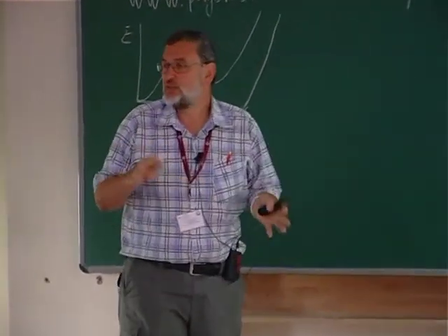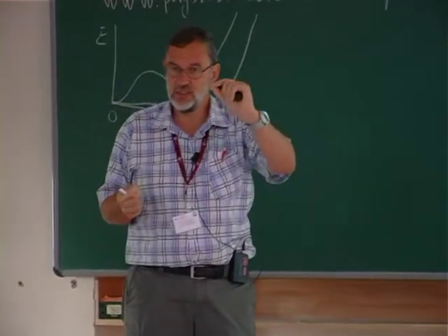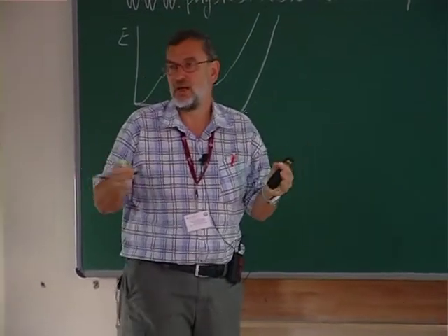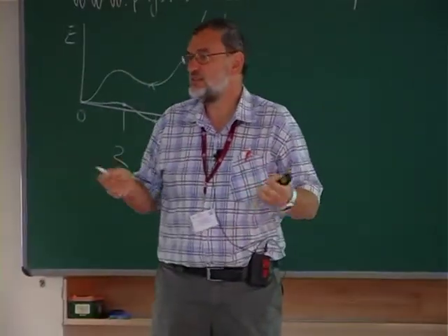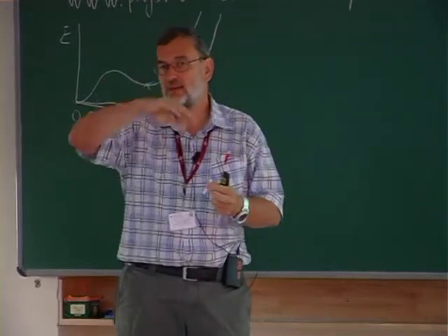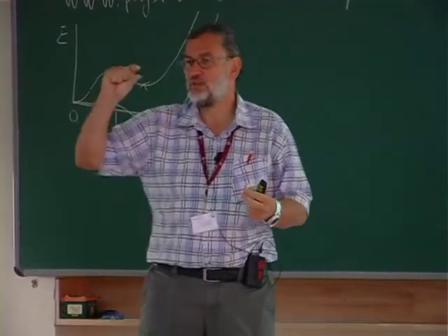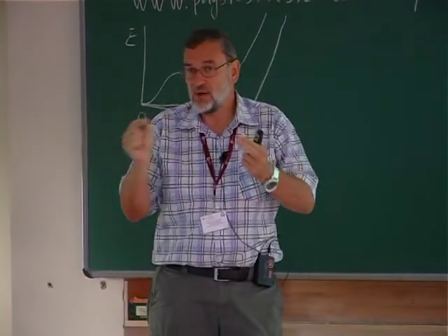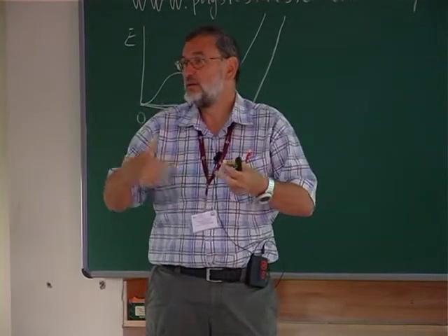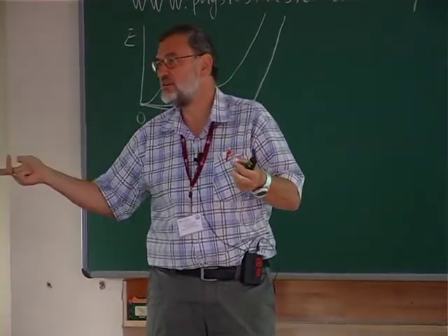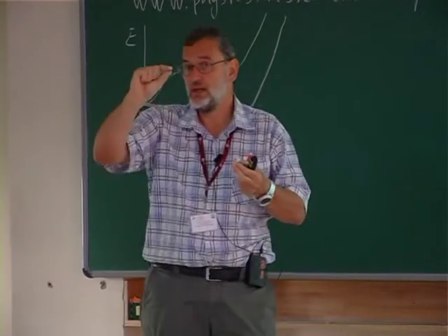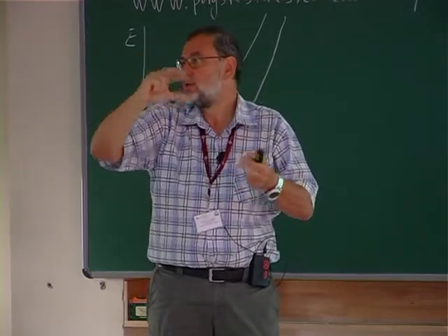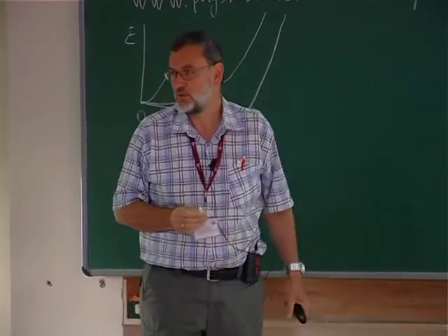And depending on symmetry or not, without inversion symmetry, it can give you a splitting of the bands. So a typical case is in semiconductors, in gallium arsenide or so, you have at the top of the valence band a 3-dimensional degenerate state without spin orbit coupling. Gallium arsenide doesn't have inversion symmetry, has heavier elements, gallium and arsenic. So if you put spin orbit coupling, it will split these 3-dimensional degenerate bands into 2 and 1 and give you this effect. Okay?